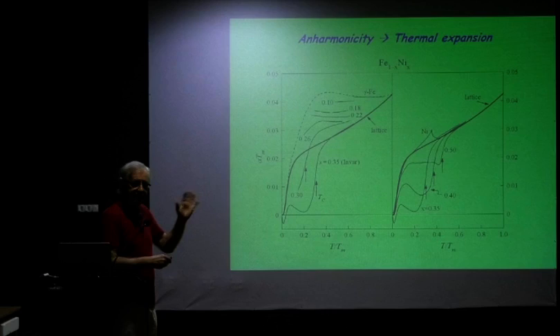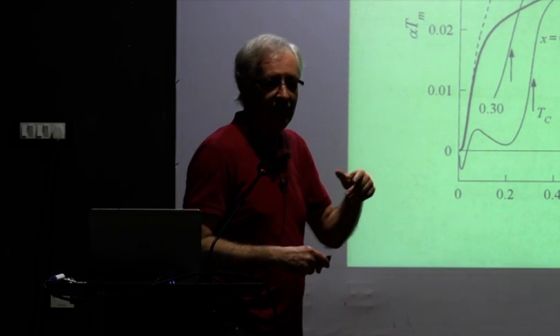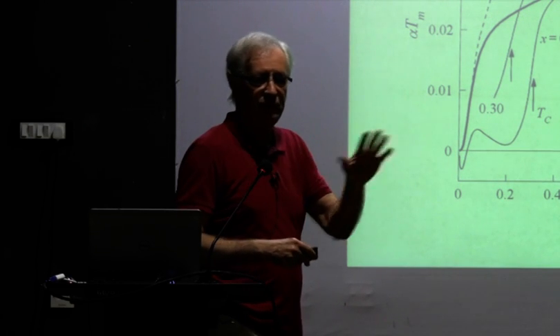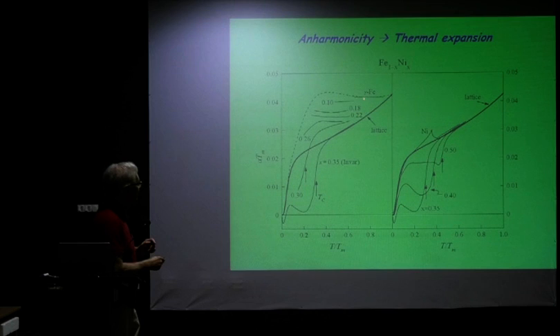This dotted line shows you what it would be if certain things are taken into consideration theoretically, but let's leave that alone for the moment. We're looking only at measurements. We have gamma iron. This below here, it's BCC. Above here, it's also BCC, so we don't look at that. And then we start adding a little bit of nickel into it. The transitions from the FCC to BCC are shifted to lower temperature, and this also to lower temperature.